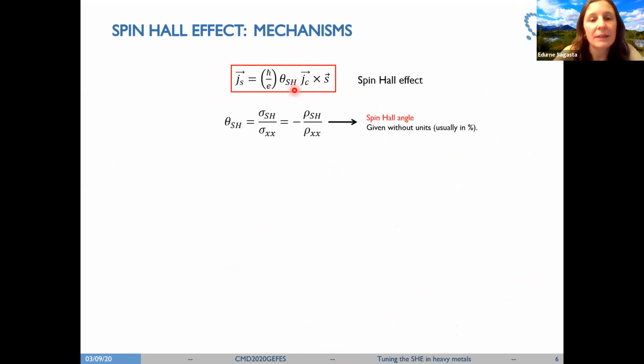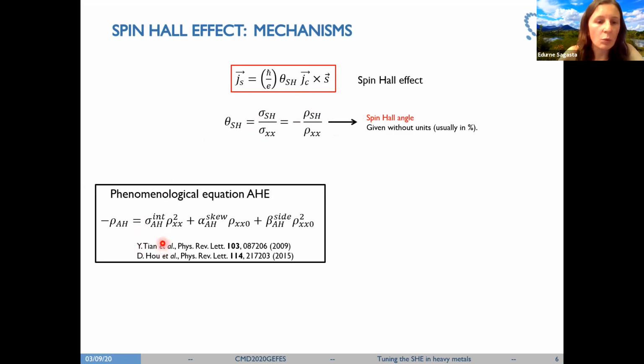And the spin Hall angle can be written in terms of the spin Hall conductivity or the spin Hall resistivity, which are the transverse conductivity and resistivity. And here we have the longitudinal conductivity and resistivity of the spin Hall metal. Interestingly, some years ago, Tian and co-workers proposed a phenomenological equation for the anomalous Hall effect, considering different contributions that explained the anomalous Hall resistivity they were measuring experimentally.